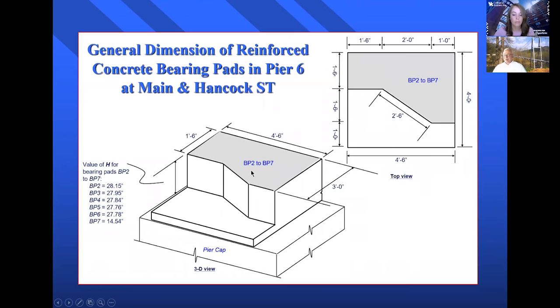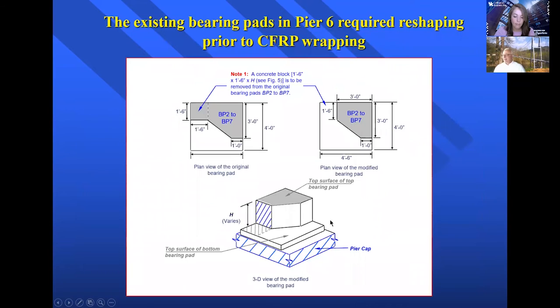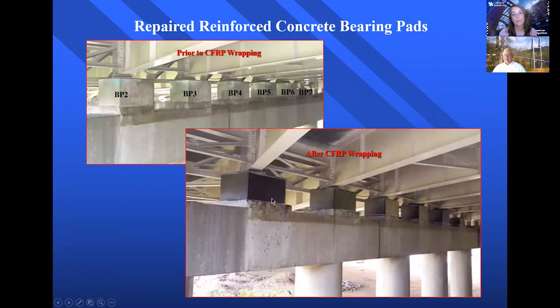And when we removed the concrete that was cracked and crumbling from one of them, we were left only with a very small portion in here. So what we wanted to do was confine the concrete to make it very strong and resisting compressive force. So we ended up reshaping the pedestals, and we confined them with carbon fiber. And this really was quite a success. First of all, it took care of any damage to these pedestals.